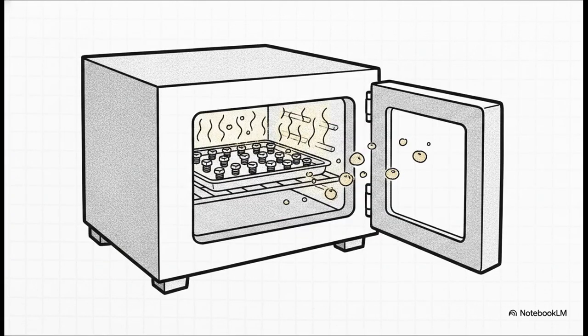Here's what happens. The hydrogen atoms are so tiny, they literally migrate through the empty spaces in the steel's crystal lattice, gathering at high stress points and drastically weakening the metal from the inside out. So how do we defeat this invisible atomic threat? We bake them, literally. Engineers mandate that freshly plated high-strength fasteners be placed in specialized ovens at 190 to 230 degrees Celsius for anywhere from 8 to 24 hours. The intense heat speeds up diffusion, forcing the trapped hydrogen to safely escape out of the metal before the fasteners ever ship to the assembly plant.